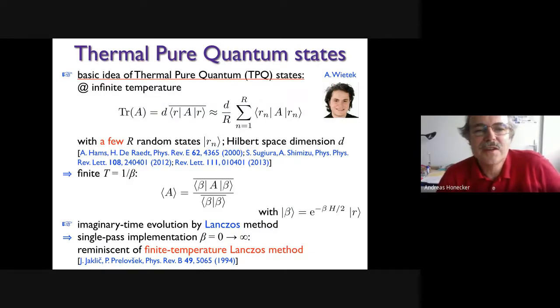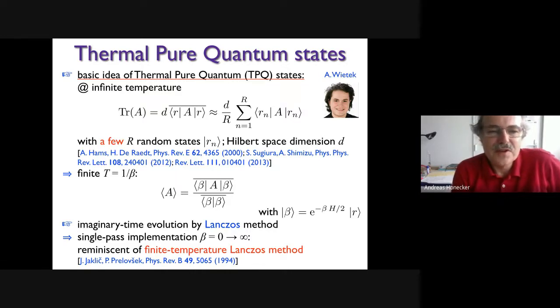That is work done by Alexander Wietek. Basically, what we have been doing here is, to go further than the 20 sites, use the idea of so-called thermal pure quantum states, which is related to the finite temperature Lanczos method. The very rough idea is that you basically estimate a trace by a random average. The trace of any observable can be estimated by a random average, and if the Hilbert space dimension is large, you can get away with very few random states. That is at infinite temperature. Then going to finite temperature, you do an imaginary time evolution, and what we do is we use the Lanczos method.